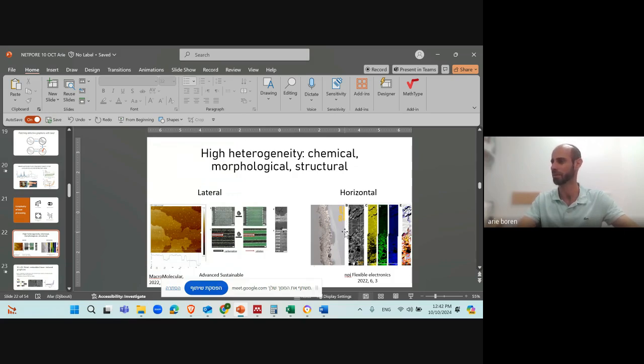I will make this a little short, so as not to make this lecture too long, but this is wonderful. We took a cross section with a resin, a cross section of the graphene loaded on a polymer or plastic substrate. So this is the graphene film, and this is just a photo image, with an optical camera.